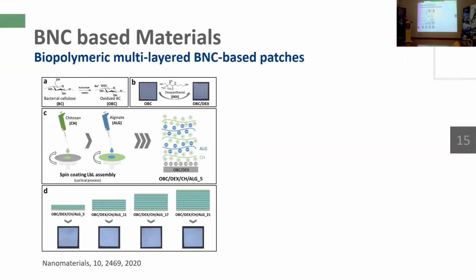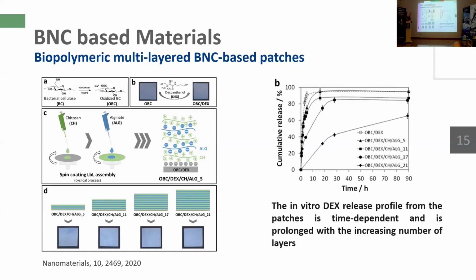In this study, we decided to prepare these biopolymeric multi-layer systems, and we achieved this by the deposition of alternate layers of chitosan and alginate, and this allowed us to prolong the release of the drug depending on the number of layers. So we can adjust the kinetics of the release of the drug depending on the number of layers, and this could be important depending on the clinical application that we desire.